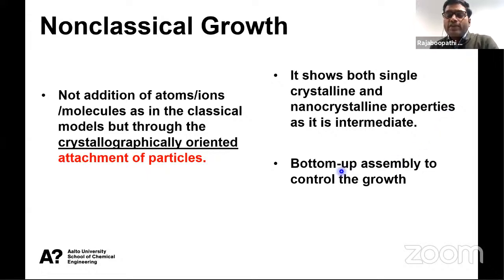And we can have some room to control the growth because it is a two-step process. In the classical case, after forming the supersaturated solution, we can get a nucleus. It is a one-step process. The only place you can control the crystallization is the supersaturated solution. But here there is a dense liquid phase, so we have some extra room to control the crystal growth. These are some advantages of non-classical crystal growth.